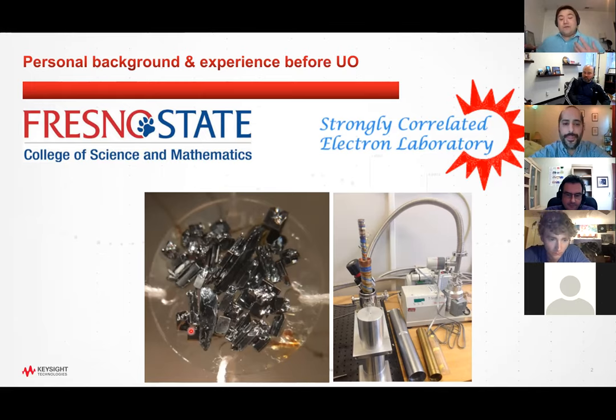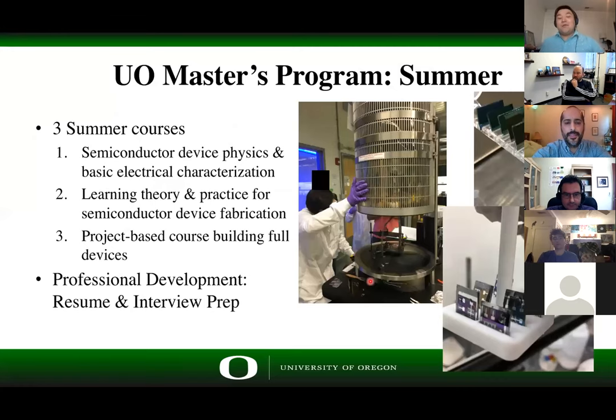And so I did a lot of trying to measure the specific heat and thermopower of material samples down to cryogenic temperatures. On the left, here's an image of one of our metallic crystal samples that's loaded on a sapphire disk for our heat capacity measurements. And here is our tabletop setup where the sample probe gets mounted here. This all gets sealed up, pumped down under vacuum. And with this system, we were able to get down to about 10 Kelvin for our measurements. And so I felt, coming out of this, having a background that was more in the area of solid state physics, it felt pretty natural to go into the semiconductor track, and also just semiconductors and the things we can make with it I thought were very interesting.